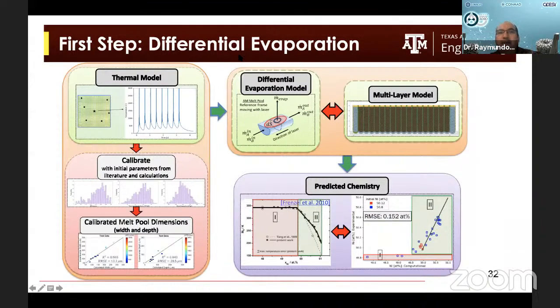And just to give you an example, this is the first step. This is work that has been recently finished by one of my students. We are about to publish it. So we have a thermal model that was developed by the Air Force Research Lab that allows us to predict the local thermal histories as you scan a part. And then, when you have these thermal histories, we go to a model that takes into account the thermal history and the chemistry to account for the differential evaporation. And of course, this thermal model is calibrated using experiments.